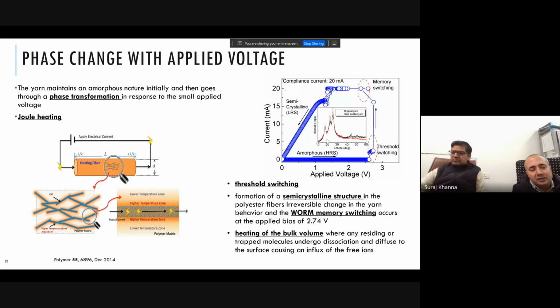So PET is typically a phase change material which can go from being less crystalline to more crystalline as you apply joule heating to it. So basically, what is happening is, in the initial part of the IV, the material is acting as highly insulating. At that time, the low value of current which is able to pass through the material is creating a lot of heat. So as the joule heating is happening, PET is transitioning from less crystalline to more crystalline.